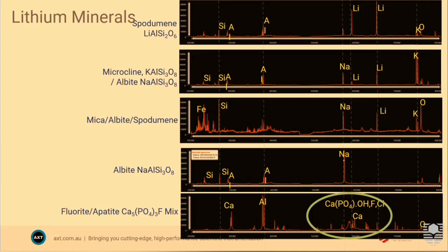X-ray technology, you're exciting the atoms right next to the nucleus, and they're quite shielded from the outer electron clouds as to what's going on around it. So if you do get mineral effects or matrix effects, it tends to be from density, dense packing density. LIBS, the electrons are on the outside of the atom, and they're greatly influenced by what's around it. And so there's lots of things that go on with LIBS. So you have the laser matter interaction, you have the matrix effects, and those matrix effects actually work in the favour of LIBS for mineralogy, because a mineral is a matrix, and in a certain commodity, you have other minerals that are associated around it, and that can affect a lot in the LIBS spectra.